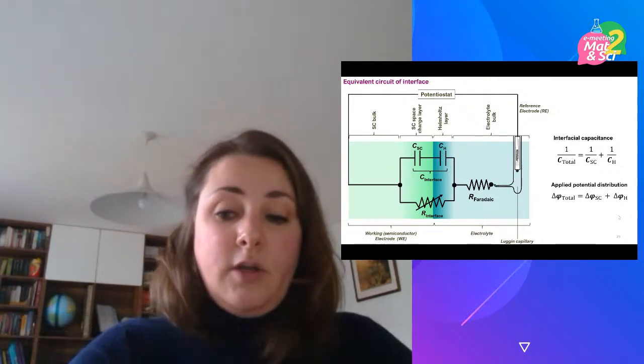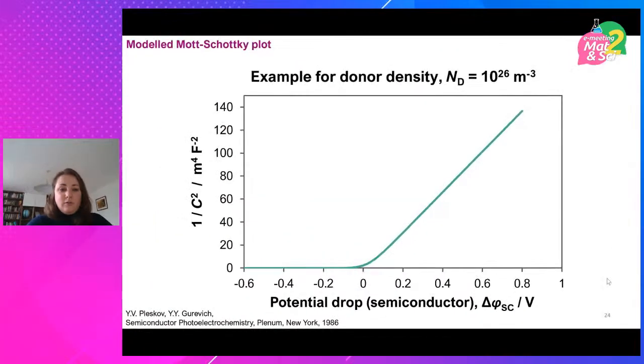So how can we illustrate this? The model that I mentioned, I'm not going to go through all the equations on the screen because that's terribly boring, but I put in the reference here to Pleskov and Gurevich. If you follow through the model and plot what an ideal Mott-Schottky plot should look like: on the x-axis, you've got the semiconductor band bending. On the y-axis, you've got 1 over the square of the capacitance. So that's your typical Mott-Schottky plot. And we've calculated the plot for a donor density of 10^26 per meter cubed. So that's a very high value. Of course, the intercept of that goes to where you have a semiconductor band bending of 0. So you just have to figure out at what electrode potential that condition is from experiments, and you're done.